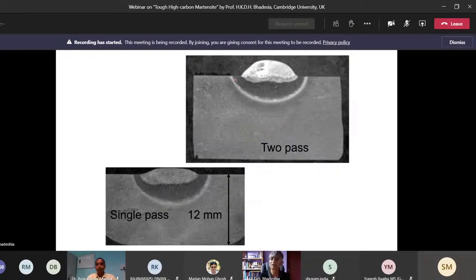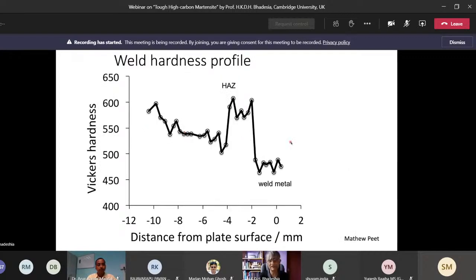Now, of course, I mentioned earlier that we cannot use a material effectively, or only in very limited applications, if we cannot weld it. So here are examples of welds on this new alloy. This is a two-pass weld and a single-pass weld, with absolutely no signs of cracking. And what is more is that we maintain the hardness. Okay, so there isn't much of a dip in hardness in the region which is tempered in the heat affected zone. We want a high strength, and we maintain that even after welding.